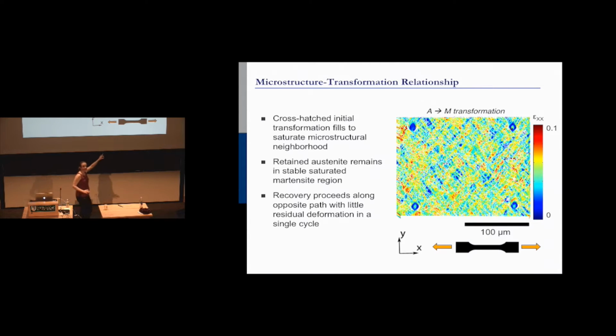And when you come through, okay, this is the other thing. Remember how Miyazaki said that when you have a grain of a certain orientation, a specific variant will nucleate and it'll take over the whole grain? Whichever variant is the most favorable will take over the whole grain. That's totally not true, and this is used in theories all the time right now. If you look at these grains, this is very heterogeneous. There are regions in this microstructure where you've got a ton of transformation up here and nothing happening over here. So there's part of the grain that's in cubic, and there's part of the grain that's not. Okay, so this assumption is not correct.